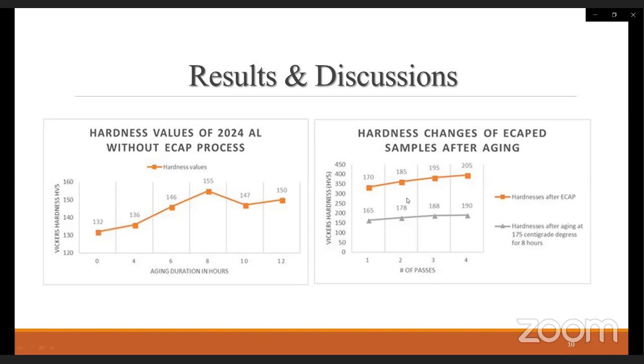So we have applied ECAP and measured the hardness values, and then we have put all these one pass, 2 passes, 3 passes, and 4 passes samples to the aging operation, and as a result of the aging, the hardness of the samples are decreased as indicated on the graphic. The higher the number of passes, the higher the decrease in the hardness value.